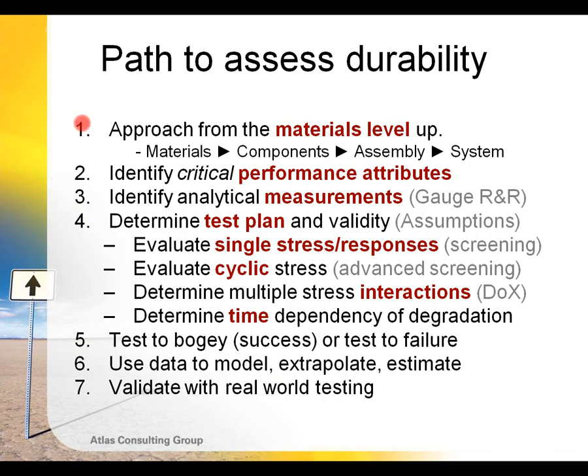So in summary, the general path to assess durability is to approach from the materials level up, identify what are the important properties we need to measure, what analytical tools we're going to use, as well as their sensitivity and reproducibility, then start determining our test plan. Typically start with single stress screening to eliminate stresses we don't have to worry about. Identify combinations of stresses and cyclic stresses. That's important to understand the possible interaction effects between stresses. And then also study the time dependency or the shape of the degradation curve with stress or time.